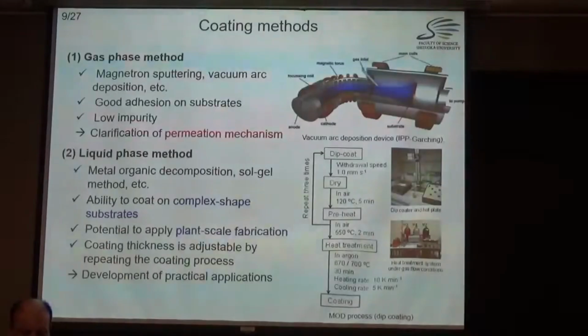Then the other side is more engineering. So the liquid phase method uses a liquid organic material. The substrate is dipped into the liquid, then withdrawn at a constant speed to coat a uniform film. Then bake afterwards to decompose the organic material, and the metal oxide remains on the substrate. So this is good for plant scale fabrication, but it is a little bit difficult to control the coating properties. So the thickness or crystal structure is not so easy. So it's more for development of practical applications.